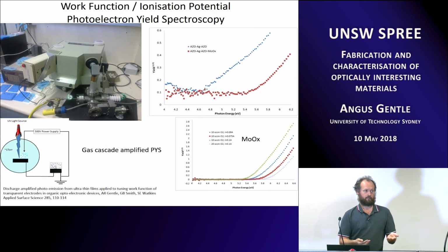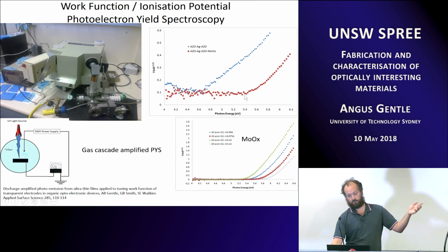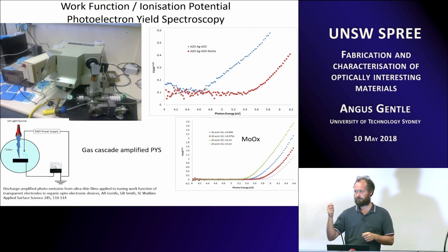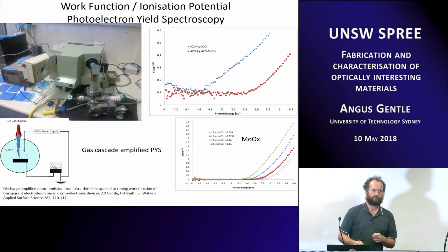So when you're doing an oxide contact, you need to know what the work function is so you can go, will it work in my device? So this will apply for any of your other materials, your devices you're making. AZO is actually quite similar to ITO. It's about 4.6, 4.7 eV for the work function. Moly oxide, ideally, to contact P3HT, you're wanting it to be 5.4 eV. Fortunately, if you take moly oxide, evaporate it in a vacuum chamber at the appropriate sort of rate, it gives you exactly the right work function.